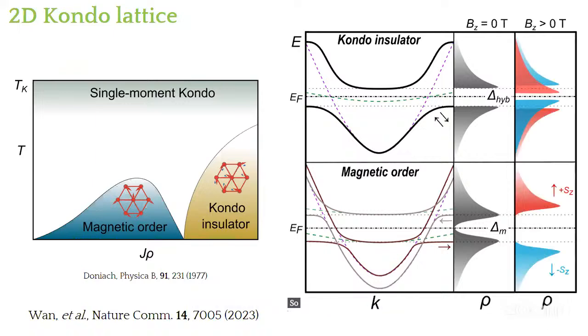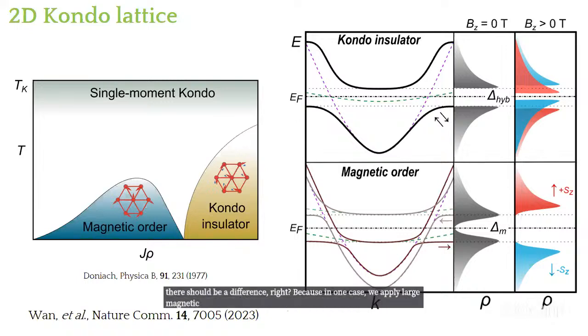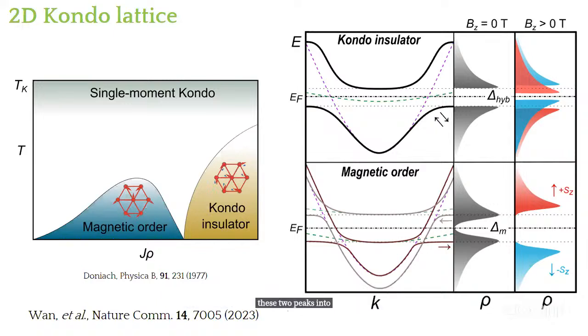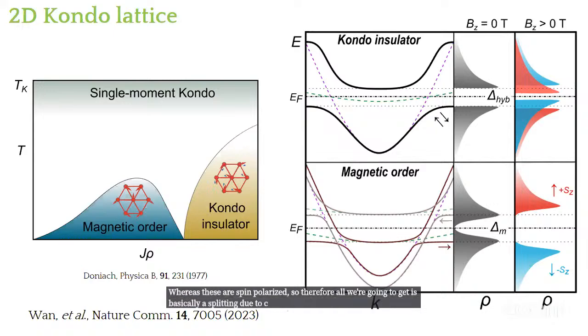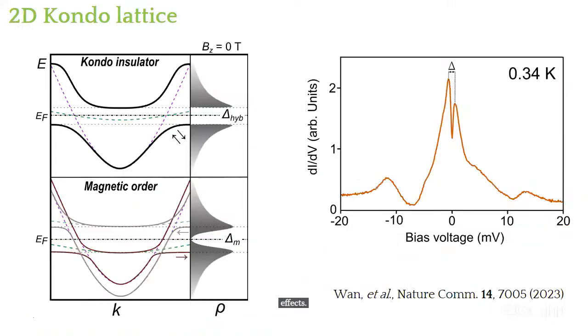So if you apply a magnetic field, there should be a difference, right? Because in one case, if we apply large magnetic fields, we should be able to split these two peaks into two flavors, whereas these are spin polarized. So therefore, all we're going to get is basically splitting due to Zeeman effects. Okay, so that's what we did.